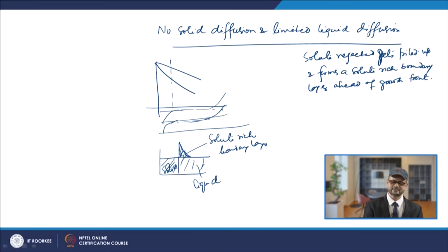So, basically this region is characterized by a solute rich boundary layer region, and in these cases the condition will be that Ds into T or Dl into T will be quite lesser than the L square values. Those will be the conditions, and initially this will be the case of initial transients.